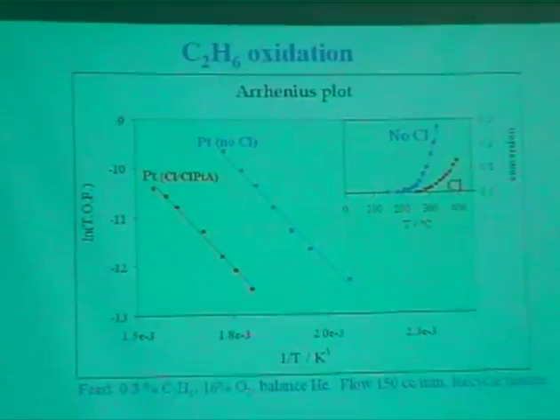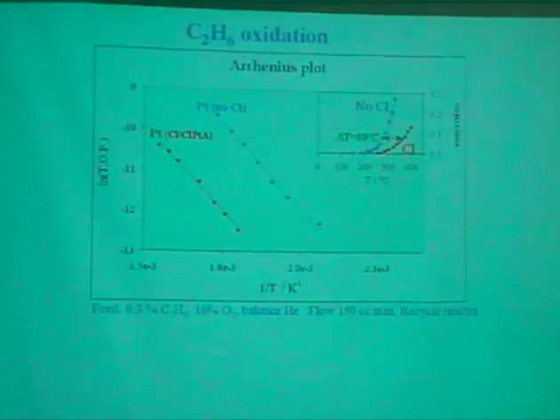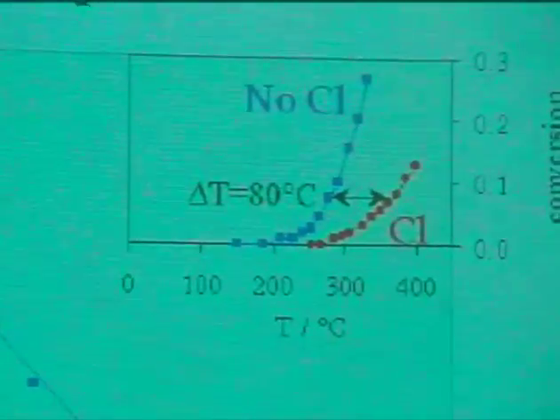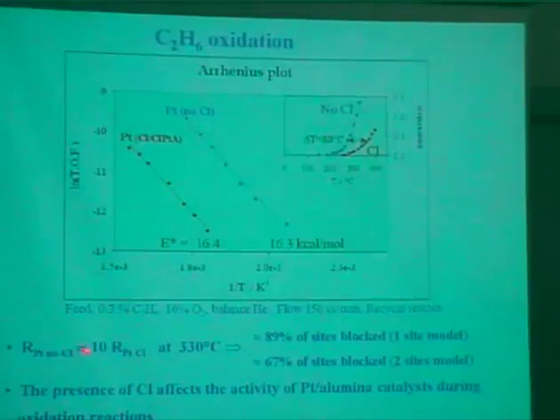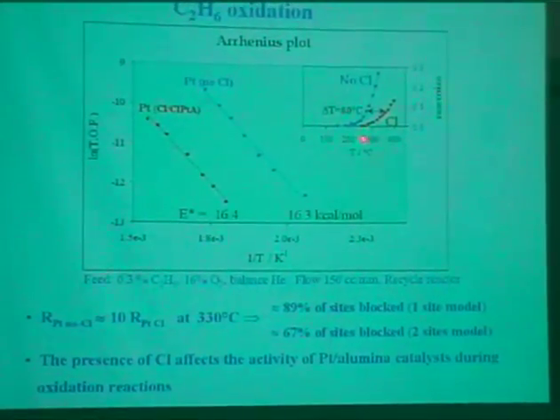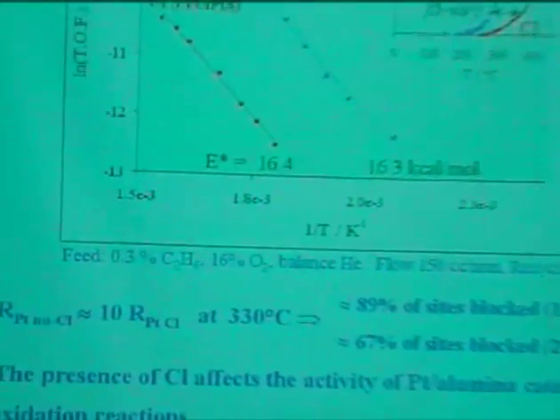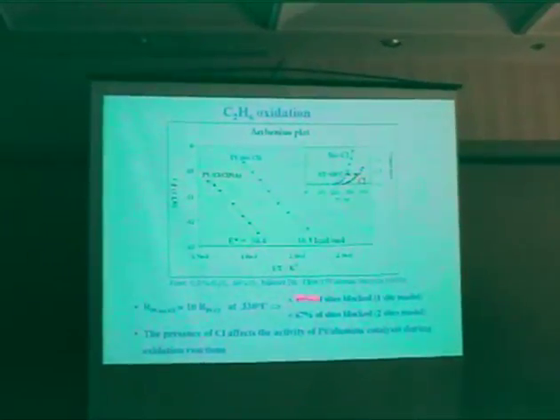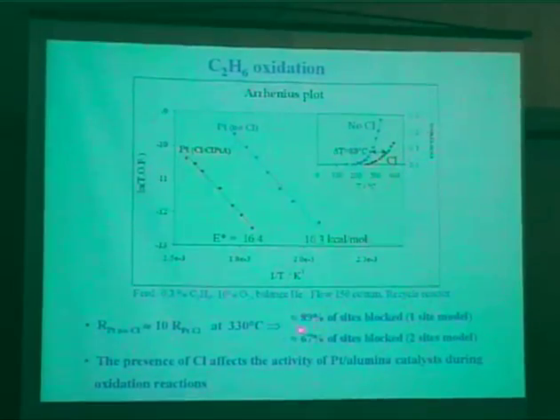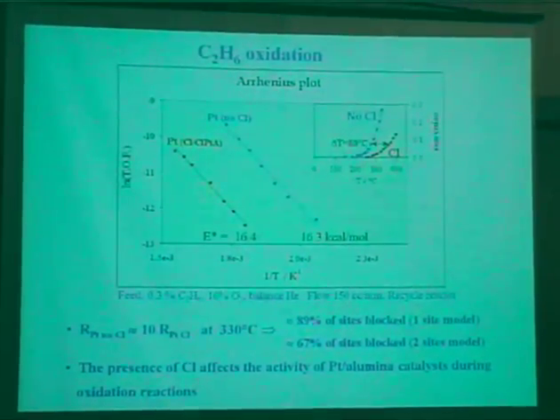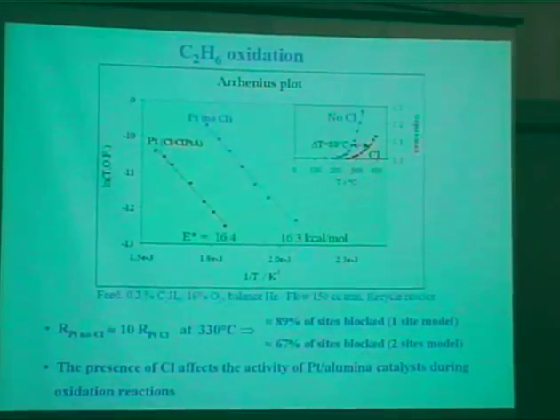Let's see what happened with C2. And sure enough, it's the same effect. The chlorine-containing catalyst is a lot less active than the one without chlorine. Activation energies here are pretty much the same. And the rate difference again is about 10. Now the temperature is different here. It's a little higher than in the CO oxidation case, and less than in the methane oxidation case. So again, if we do these calculations at this particular temperature, we get about 90 to 70% of sites blocked by chlorine. So chlorine is a poison for oxidation reactions under these conditions.